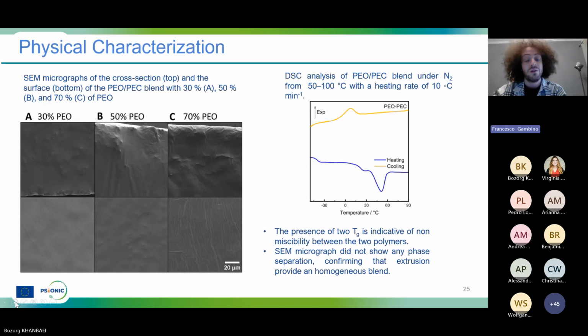After the production of all of the membranes, we started with the physical characterization, and we examined the morphologies of the polymeric blend composed of PEO and PEC by SEM analysis. The micrographs on the left show the cross-section and surface analysis of the blend at 30, 50, and 70% of PEO and PEC. All of them displayed a uniform and continuous appearance without evidencing any separate domain. This suggests that the PEO and PEC components are well homogenized and that our extrusion process is working well to produce this blend polymer electrolyte.